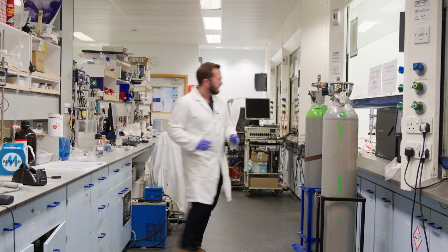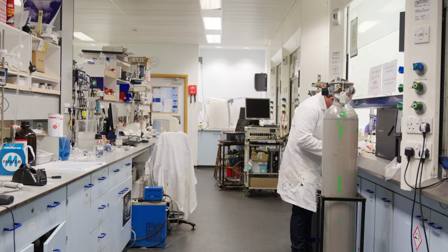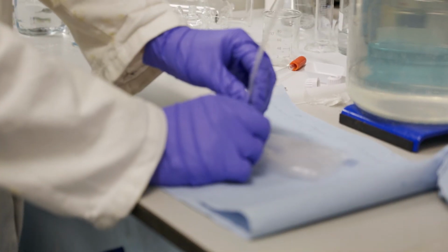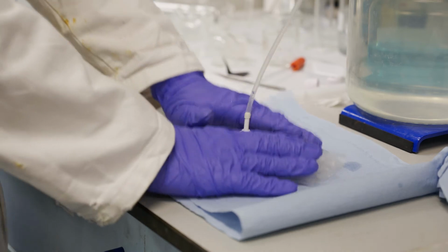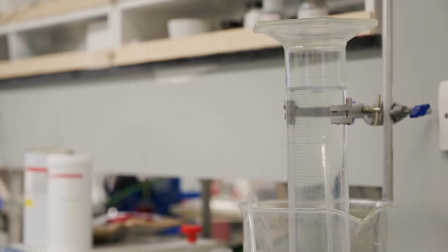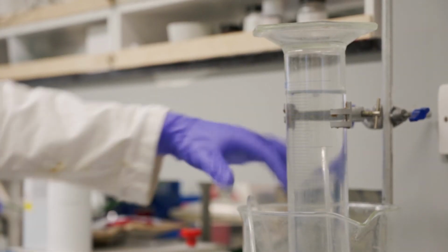The first part of the role is looking at these manufactured copper gas diffusion electrodes and just trying to work out which the best manufacturing technique is. And that means we can then feed back to our partners and say, based on this analysis of all of these different conditions, we believe that when you want to do your experiments on your much larger setup, you should focus on these 3 or these 5, which look to be the most promising.